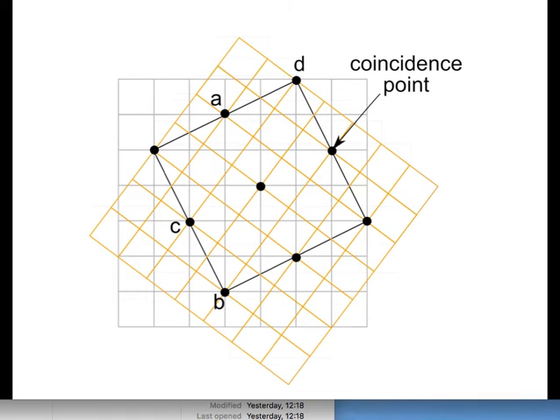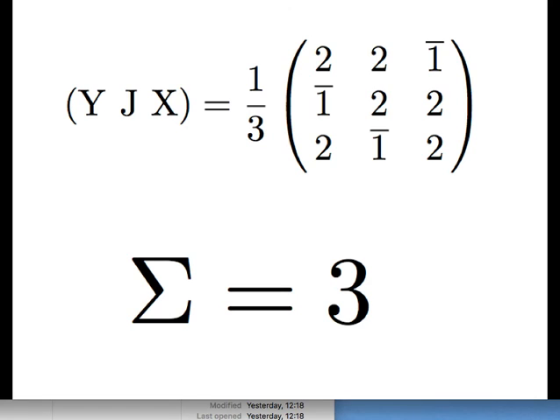So if I have a rotation matrix describing the orientation between the gray and the orange lattices, and I multiply it by a vector equivalent to the coincidence site lattice, for example 2, 1, 2, then I should get an integral vector. So if I'm given a rotation matrix like this, and I find a factor which converts everything inside the matrix into an integer, and I take it out, like the 1/3 over there, then the inverse of that gives me the sigma value. If you can find a common factor which converts everything inside that rotation matrix into an integer, then 1 upon that common factor will give you the sigma value. Everyone happy with that?